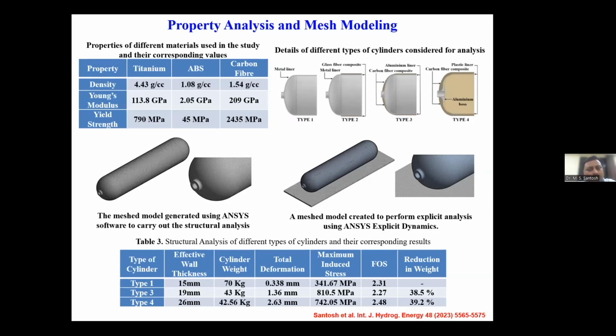There are new R&D developments that are happening in the type 5 category as well, where there is no overwrapping on the surface of the liner material. The liner material itself will be strong enough and capable enough to hold the hydrogen under high pressures of 350 to 700 bar. When we came up with the material design of ABS, that is acrylonitrile butadiene styrene, and tested it as a basic polymeric material,